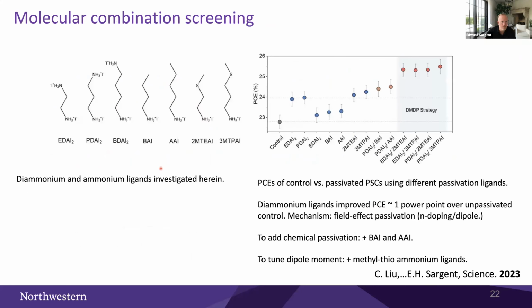So he began by screening a number of candidate diammonium and ammonium ligands, and you'll see some interesting trends here on the right. Of course, we already know that the diammoniums like the EDA and the PDA do increase the PCE of systems, in this case by about 1 percentage point in this study. He then added a chemical passivation with BA and AA. But then he started to look at the methyl thioammonium ligands as a means to tune dipole moment and got some pretty interesting results. You'll see here through these mixed strategies, combining a diammonium and the methyl thioammonium, a notable increase in the power conversion efficiency.